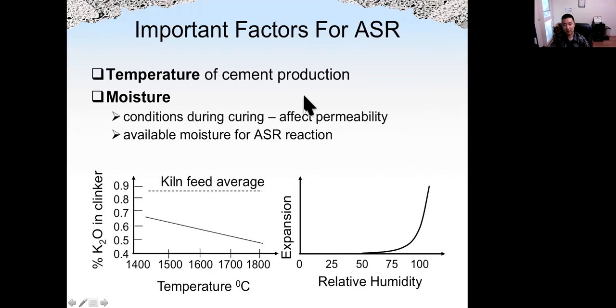Okay. The temperature of cement production may also be a factor, because the temperature during the production of cement in the kiln will affect the percentage of potassium oxide, which is another type of alkali in the clinker. And moisture, so the condition during curing. At early age, moisture curing is good because moisture curing will reduce the permeability. So lower permeability is better for ASR, actually for all types of potential durability issues. But at later age, we should try to limit the amount of moisture if possible, because with no moisture, we don't even need to worry about the potential for ASR.